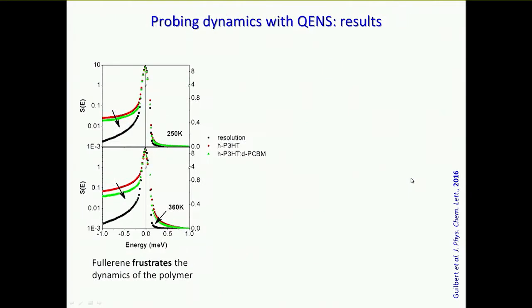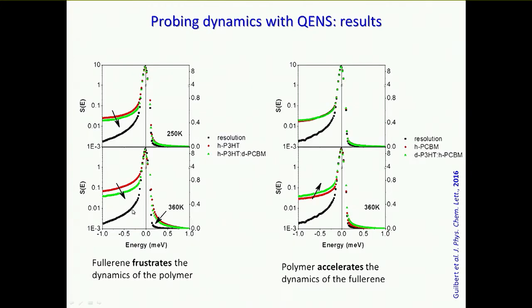Then we could ask the question, what happens to the dynamics of those molecules when you put them into the blend? The answer was quite interesting. When you put fullerene into a polymer, it slows down the dynamics. So fullerene frustrates the polymer. When you put polymer into the fullerene, it actually makes it easier for the fullerene to move. So the fullerene effectively acts as a plasticizer for the polymer, whereas the polymer effectively vitrifies the fullerene. This very clearly says that the properties of the blend are not simply the sum of the properties of the individuals, but they have a specific interaction.